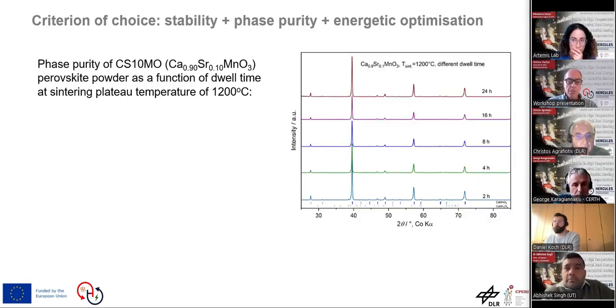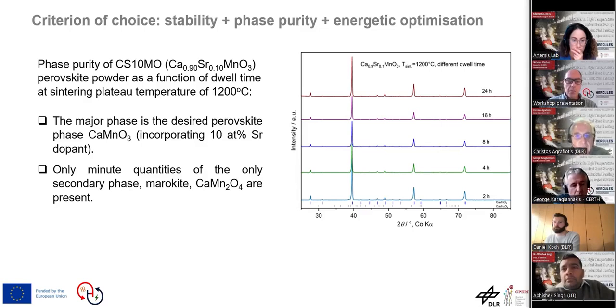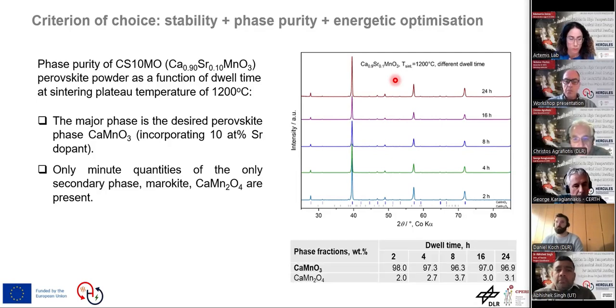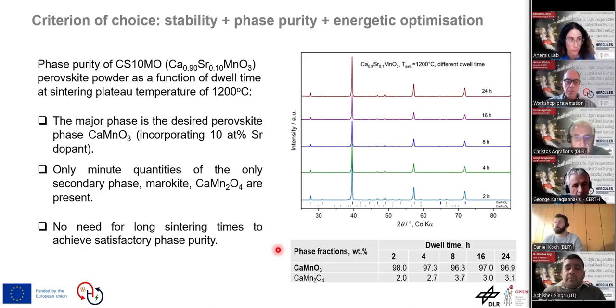For instance, the first criterion is phase purity and energetic optimization. Here we see the phase composition of a strontium doped calcium manganite perovskite as a function of the sintering plateau time, which varies from 2 hours to 24 hours. And we see that for this composition in these conditions, the major phase is calcium manganite doped with strontium. All the samples are single phase with minute quantities of a secondary phase. And if we click, we can also see, by calculating the purity of the phase, that it is almost pure perovskite phase-wise, and we don't need very high sintering times to achieve that. This can be achieved even in the first 2 hours of sintering.